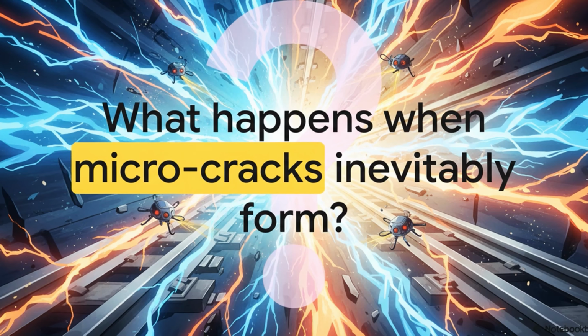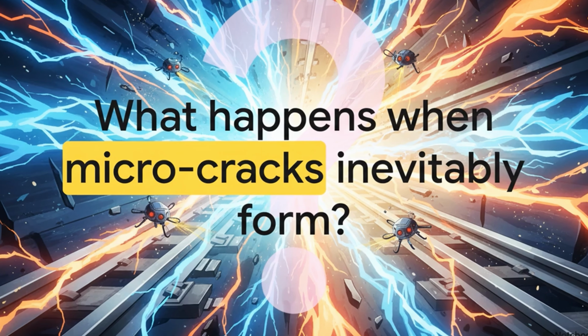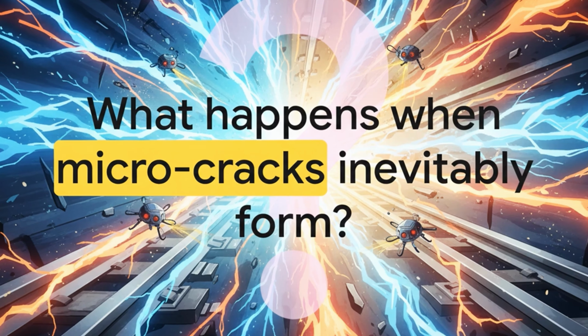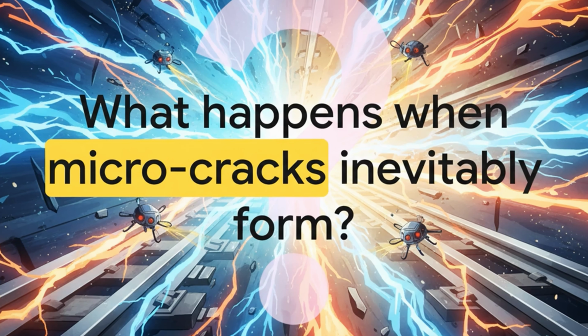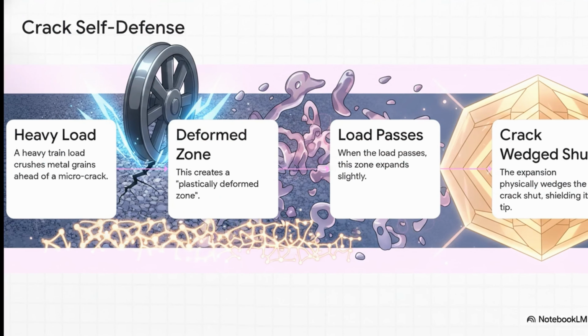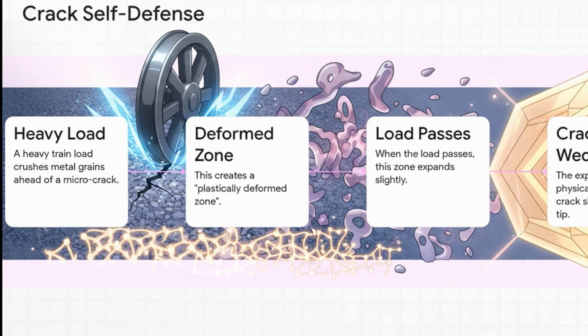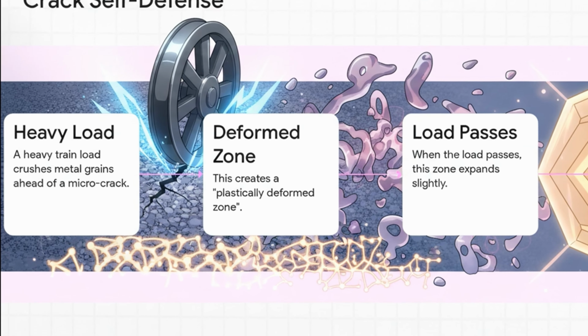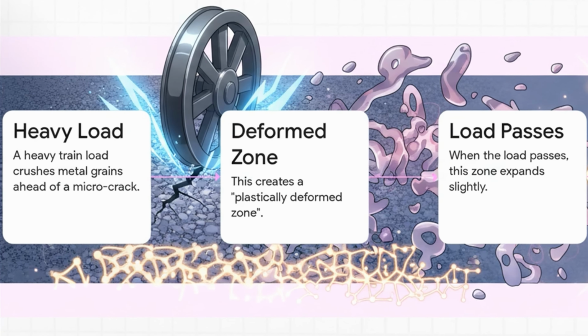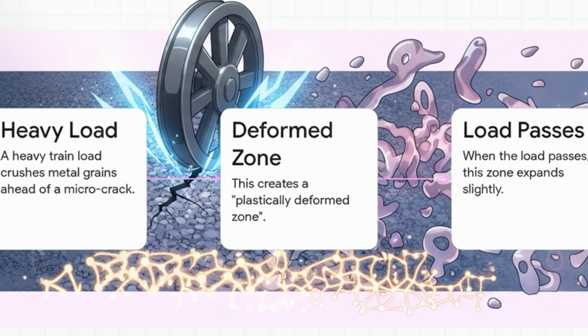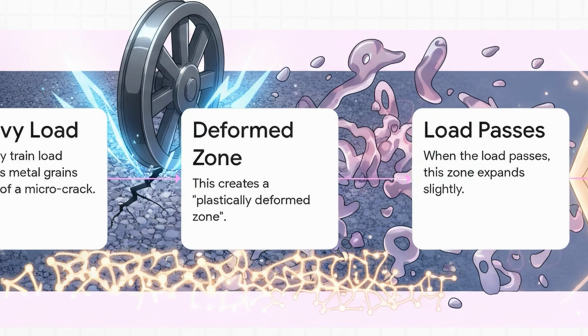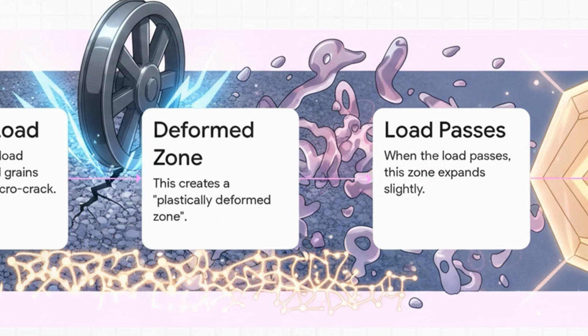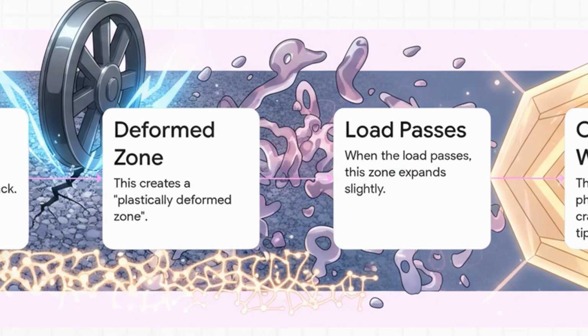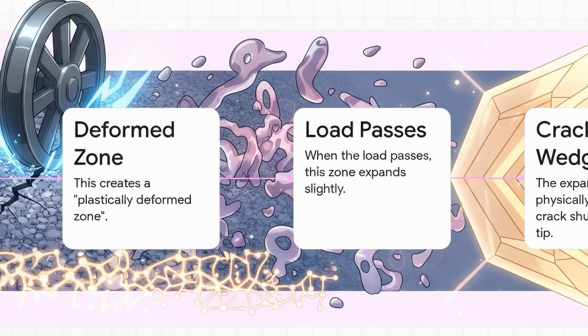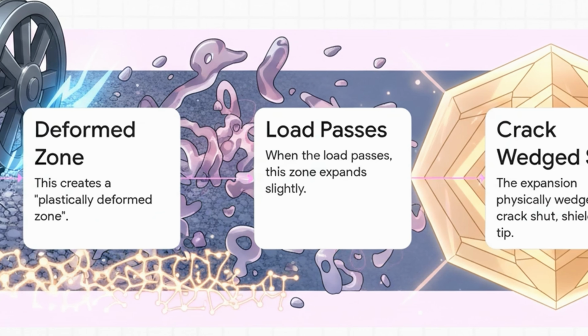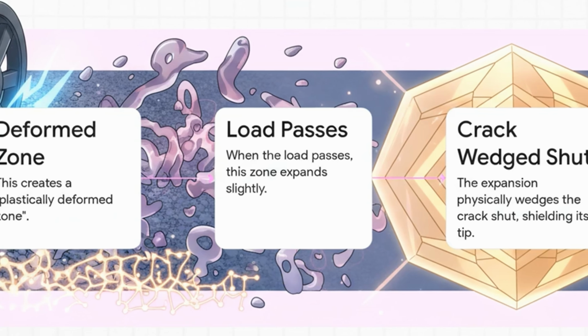An amazing stat for sure, but here's the thing, no material is perfect. After all that punishment, over all those years, tiny microscopic cracks are going to start to form. It's inevitable. So, what happens then? Does the rail just snap? No way. This is where the steel gets really clever. It actually has a built-in self-defense mechanism. Check this out. As a train wheel rolls over, its immense weight crushes the metal grains right at the very tip of a tiny crack. Then, as soon as the wheel passes, that crushed zone kind of expands back a tiny bit, and that expansion physically wedges the crack shut, shielding the fragile tip and stopping it from ripping any further. The steel is literally slowing down its own death.